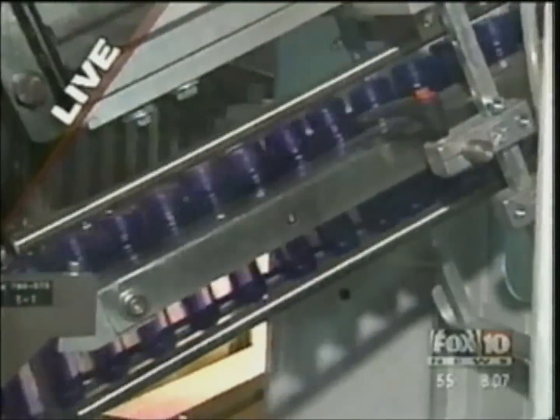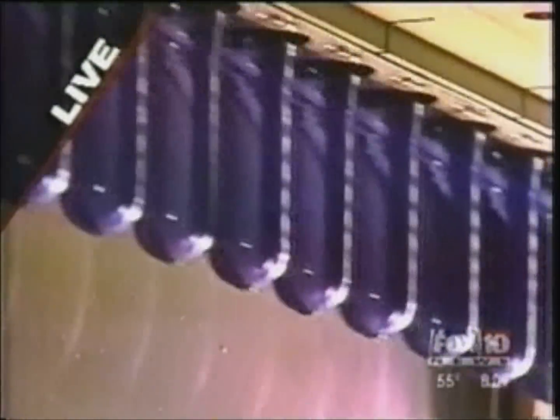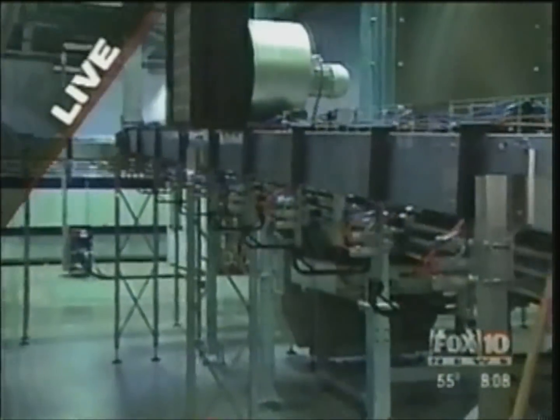Jerry's still with us. We're going to go from this preform to the full-blown bottle in just seconds. First you shove them in an oven, right? You heat up the preform so it becomes blowable. Then after it heats the preform up, you go into the blowing machine. Inside the blowing machine there's a mold — this particular machine has 16 cavities — so you're making bottles by blowing with high pressure, 600 psi, and it comes out as the finished bottle. They're going so fast — it's a 1,000 bottles-a-minute line, and this is the conveyor that takes the bottles to the production filler.